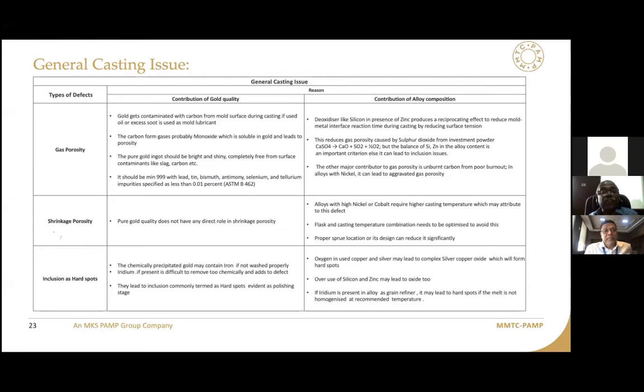Now, inclusions as hard spot. If your gold is precipitated with ferrous sulfate and you are not washing it properly, you will get iron. At the same time, if it is having iridium, it will definitely lead to inclusions entrapped into the cast surface. So when you polish, you will find that this is coming out as a hard spot on your polished surface, especially the lapping surface.